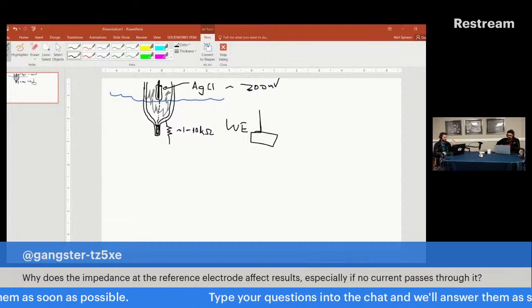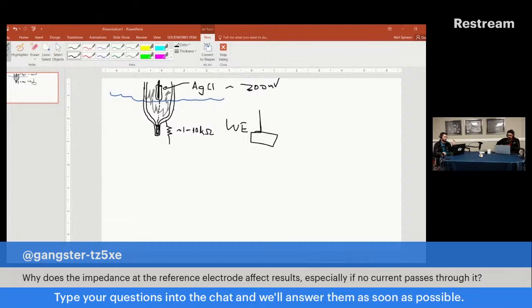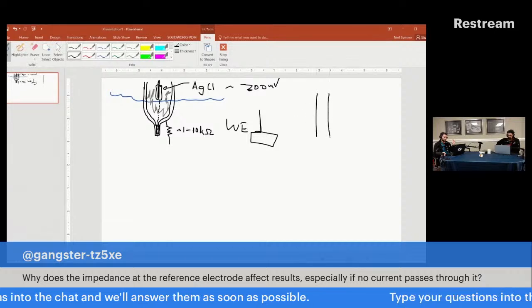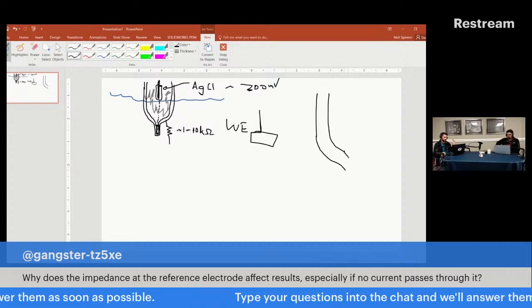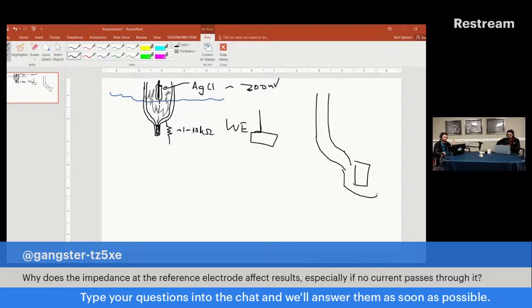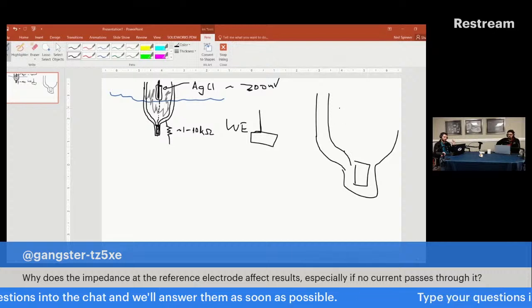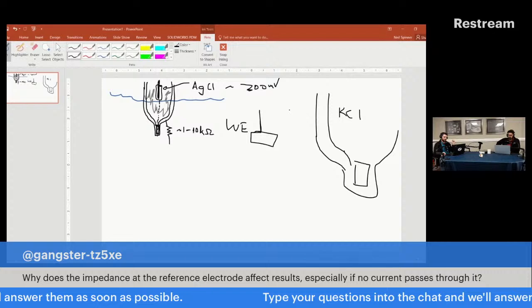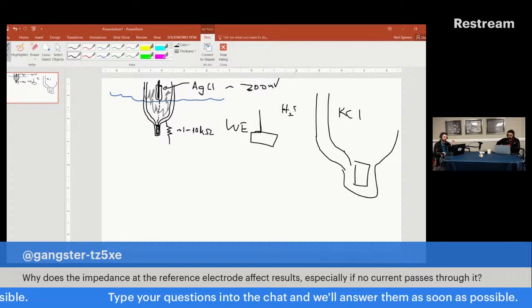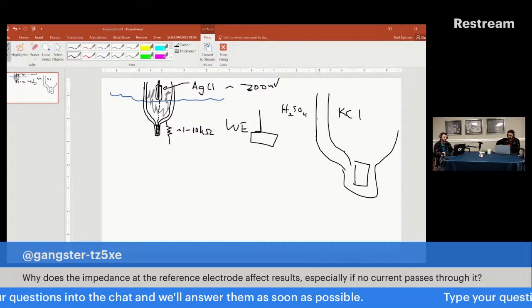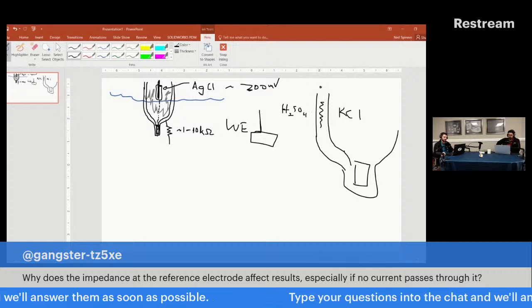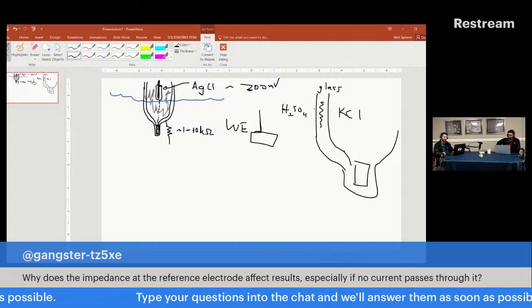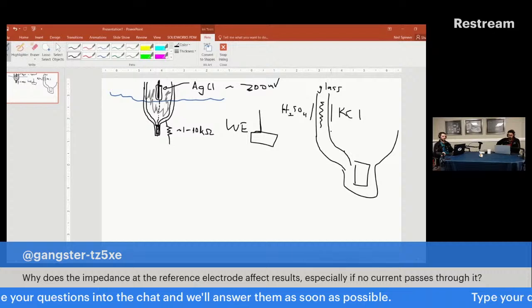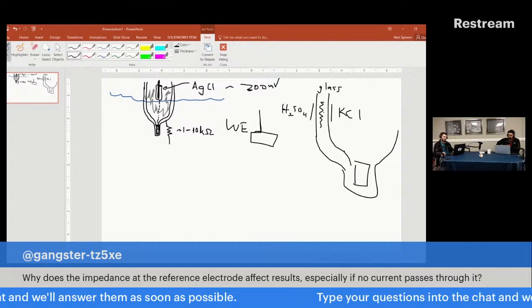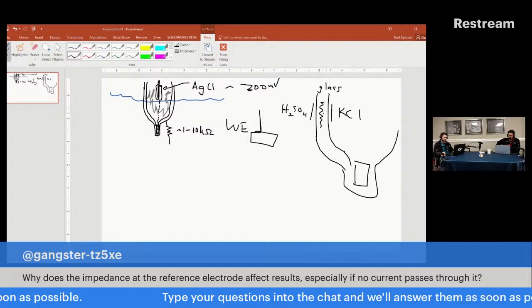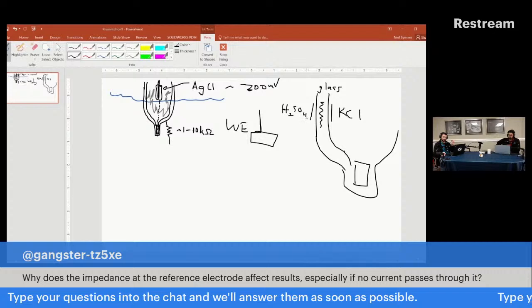What we have in a very weird counterintuitive way is through the glass wall of our reference electrode. This is just a zoomed in version of the reference electrode, right? Okay. Through the glass wall, we have KCl here. We have whatever our electrolyte is over here, H2SO4, whatever it is, doesn't matter. This is glass, right? It's some glass body. We actually have a capacitor here. Okay, we have electrolyte on both sides, and we have a material separating them. That's glass. Glass has a dielectric, and it actually is a capacitor.